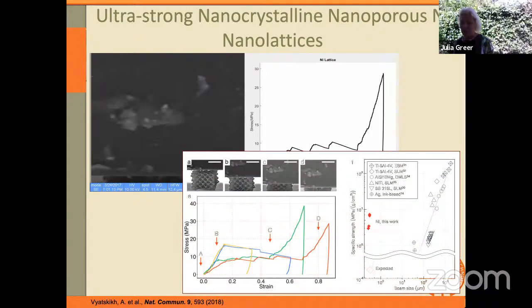But here's something interesting. When we compare the specific strength, and what I mean by that is the strength normalized by density, of a bunch of typical metals, so this is titanium, aluminum, silver, and some other alloys, for a variety of commercially available additive manufacturing methods, what we can see is how quickly the strength deteriorates as a function of the feature size. For example, most commercial techniques are able to produce 1 millimeter features very well, and you can see the strength is very high. But as you reduce it from 1 millimeter to 100 microns, just simply a factor of 10, you can see that your specific strength falls by 2 orders of magnitude.